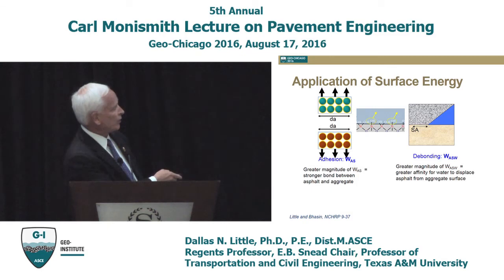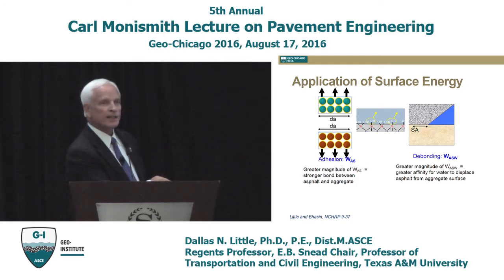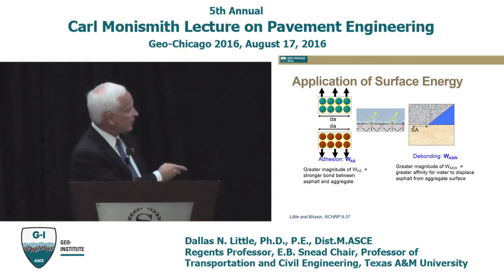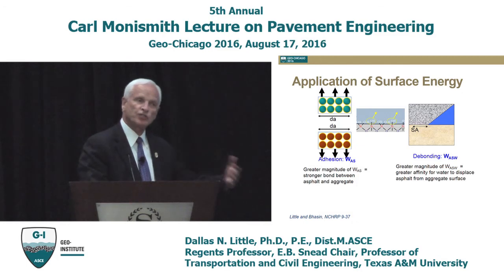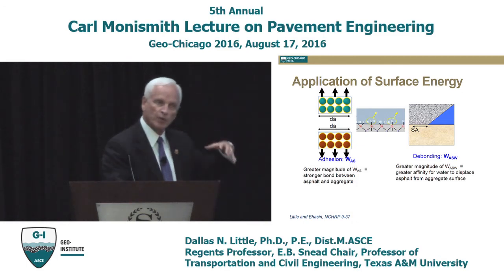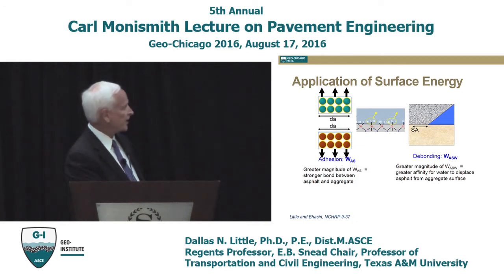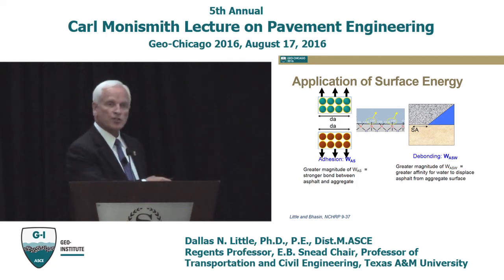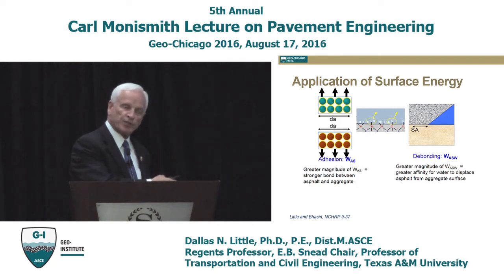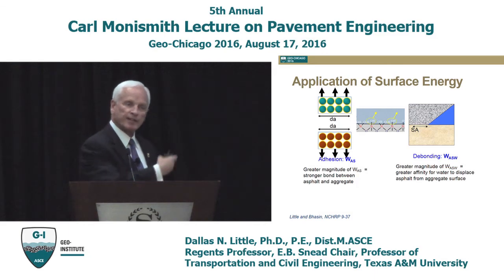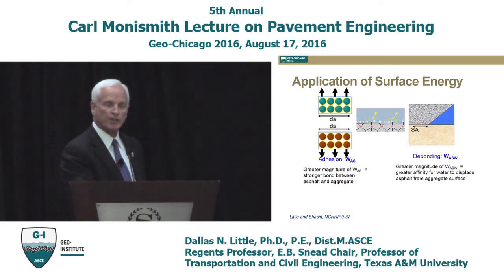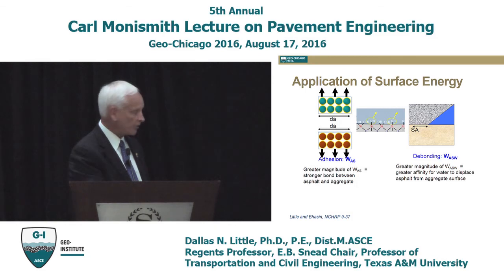And here I've given you a little simulation. If you have a silica aggregate, then normally the high surface energy is because of these unbonded hydroxides. And so the asphalt is going to want to bond with that because of its polar components bonding with the surface of the silica. And that's what causes surface energy of both, the free bonds, and so that can be used to calculate the work of adhesion between the stone and the asphalt.